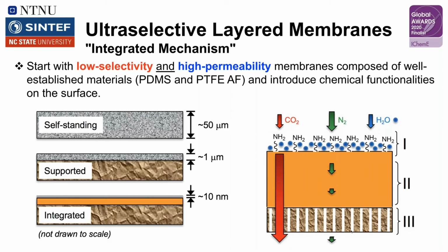And the idea here is that if we look at traditional ways of producing organic membranes, they can be self-standing, so that we're looking at thicknesses on the order of about 50 microns, or they could be supported by a macroporous support. And now we look at only thin films measuring maybe about 1 micron, so they do need mechanical support. What we're looking at is taking this idea and extending it one further. And that is, we're going to decouple the properties of this supported layer such that we now have a high permeability layer and a high selectivity coating on the surface. And this coating is only on the order of about 10 nanometers.